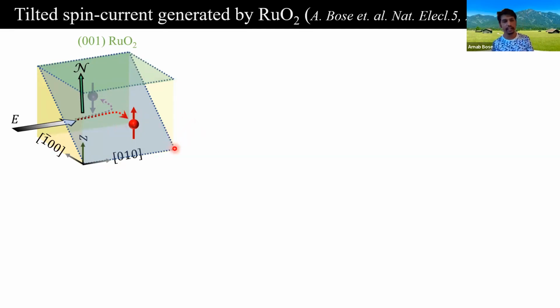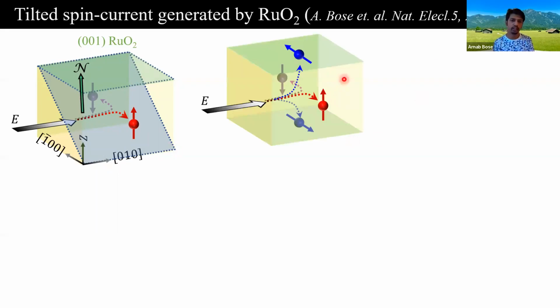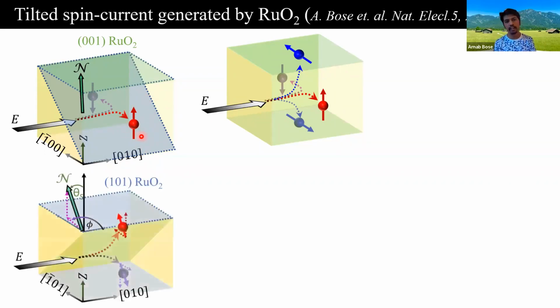Now you may again think that it is similar to spin Hall effect, but it is completely different because for the spin Hall effect, we have spin current in all the planes. It goes up and it also goes sideways, unlike this case. Here, the direction of Néel's vector determines the polarization of spins. Now, we find that if this theory prediction is true, then it should create very different sort of spin current in another plane, which is the 101 plane. This shaded blue area is the 101 plane.